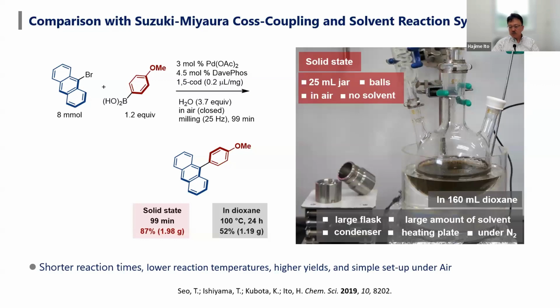We should use very large glassware, and this reaction should be conducted under argon or nitrogen atmosphere. This glassware also needs condensers because we are heating up these reactions, and of course heating with oil baths is also required. But even with these reaction conditions, the reactivity is not so very nice - after 100 degrees Celsius reaction temperature and 24 reaction hours, only 50% product was found.